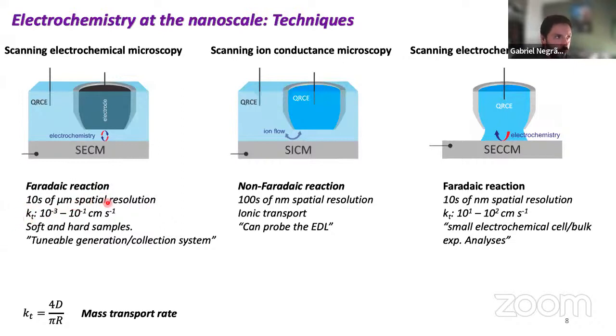This is important. I think Mauro talked to you guys about the kinetic transfer rate, and this is a parameter related to the mass transport rate of those electrodes. If they are in this size range, we're talking about these kinds of transport rates, which will limit the forward rate transfers, or the k0 for instance, in the Butler-Volmer equation that I can probe. If you remember from our slides, I need my system to be either limited by diffusion or limited by the kinetics, right? So this limits how fast a kinetic reaction or surface reaction I can probe. Just bear in mind that all those techniques have their limitations and considerations, and this is mainly because of the size of the electrode.